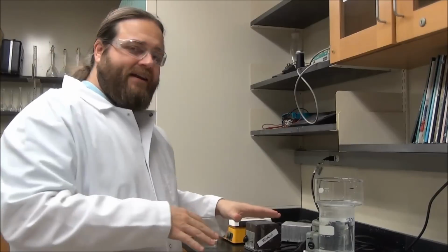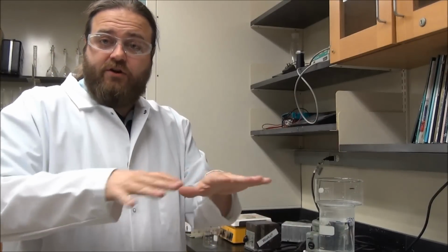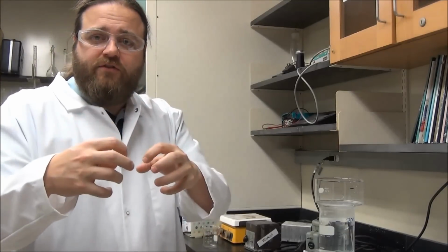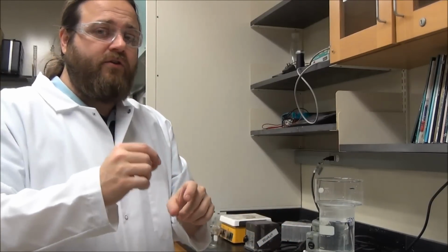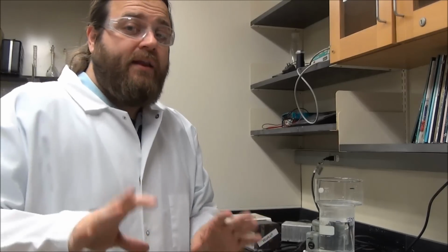Secondly, if something bad does happen, that is, your solution crashes out and you get a bunch of new little crystallites, if your crystal's sitting on the bottom, it's going to get lots of crystals stuck to it, whereas if it's floating in solution, hopefully any crystals that form will fall off to the sides and not necessarily stick to your crystal. So if it does crash, you can pull your crystal out, reheat the solution, and then once it cools back down, put it in. So again, the good news here was that the solution didn't really crash out. Our crystals grew a bit overnight, which means it's supersaturated. The amount of water means these crystals will grow.